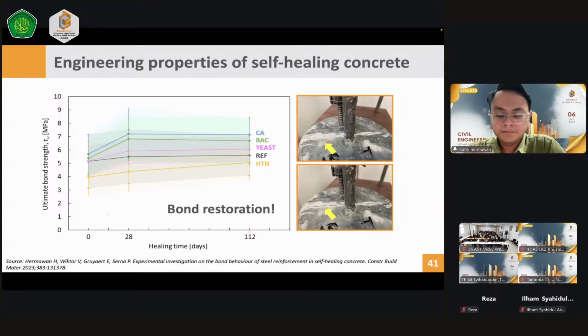And why does it happen? Because actually the healing products are still quite weak. They cannot really bridge two sections of the material after cracking. So it needs certain time until the healing products can have a very dense packing, and also a good bridging effect between those two surfaces of the specimens, especially within the cracks.